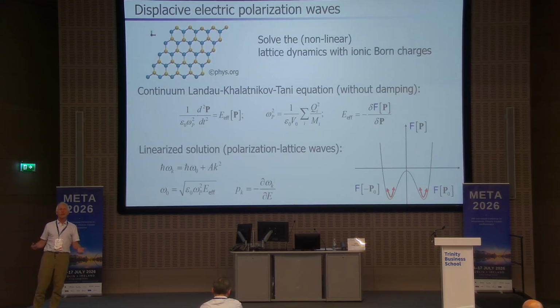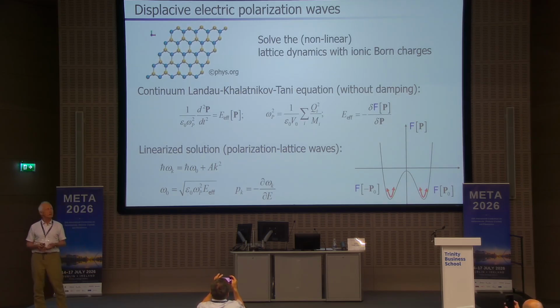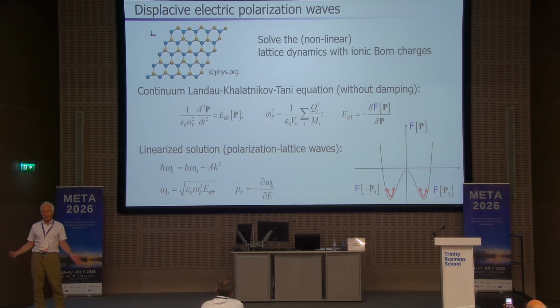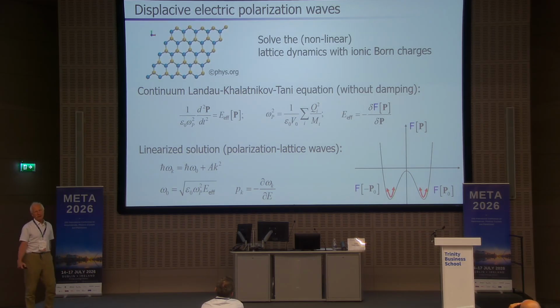If you want to understand ferroelectrics, we should solve the lattice dynamics of the charged particles. Again, this can be quite complicated, especially if you have important nonlinear terms. So also in this case, we can make a continuum approximation, and we then arrive at a Klein-Gordon-like equation, which goes by the name of Landau-Khalatnikov-Tani equation.